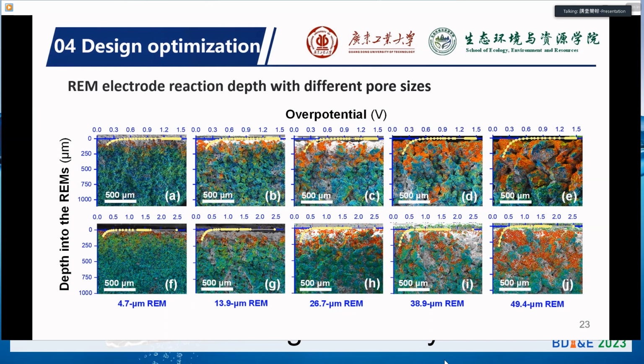The yellow dots are the model results, and the red part represents the catalytic reactive zone, visualized by the lead imprinting methods. So at a smaller hole size, too, we had enhanced mass transfer character of the REM, but the reaction zone is only constrained at this very small zone beneath the electrode surface.